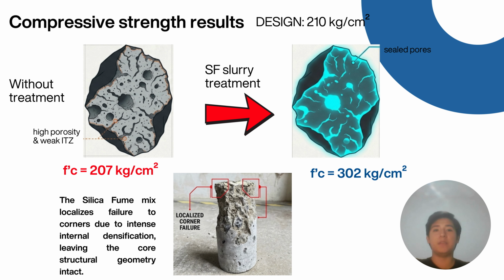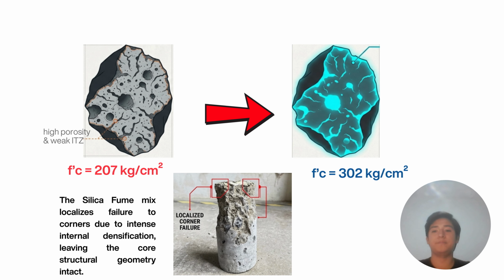These results indicate that the silica fume treatment effectively improves the microstructure of recycled aggregate by sealing pores and strengthening the interfacial transition zone. Also, it's important to analyze the image below, which exemplifies how the failure goes on. The silica fume mix localizes failure to corners due to intense internal densification, leaving the core structural geometry intact.